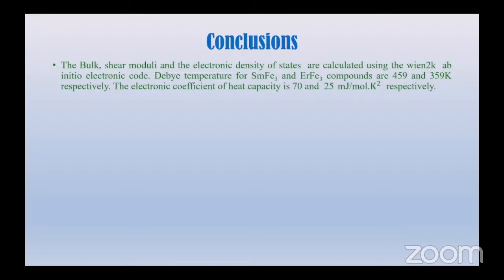Conclusion. The bulk and shear moduli and the electronic density of states are calculated using the WIEN2k ab initio electronic code. The Debye temperatures for samarium iron 3 and erbium iron 3 compounds are 459 and 359 Kelvin respectively. The electronic coefficient of heat capacity is 70 and 25 millijoule per mole per Kelvin squared respectively.